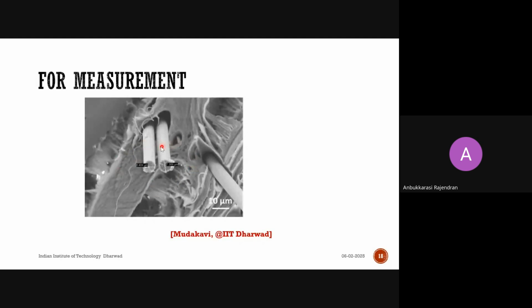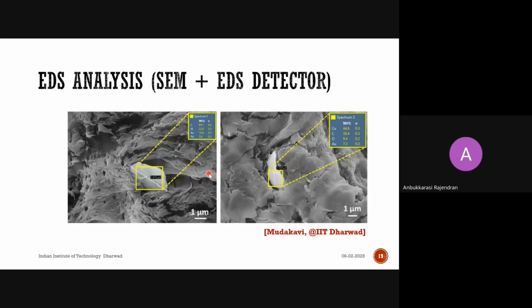And in addition to analysis, for a polymer embedded into the matrix, by using SEM we can measure the size of the particles, also fiber. Same way, this is another feature in one of the matrix. So the size also is measured by using SEM. On top of that, if I want to understand what particle it is, I can see the particle is present in the matrix, but I'm not aware what particle it could be. So I have to go for another additional support that is called the EDS detector.